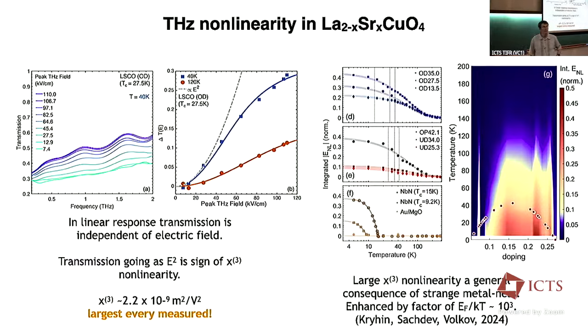There are a few possibilities. One, within the theory of conventional metals, is large non-parabolicity in the band structure, which would be enhanced at 0.2-ish, because that's where there's a Lifshitz transition where the Fermi surface goes from being closed around pi to being closed around gamma. That should have the largest non-parabolicity, but it doesn't seem particularly peaked around 0.2, as you were pointing out. The other possibility is large inelastic scattering, or energy dependent scattering, to say it better. Overdoped cuprates are perhaps less interacting than other ones, but they're not weakly interacting metals. I think that's the essential thing.